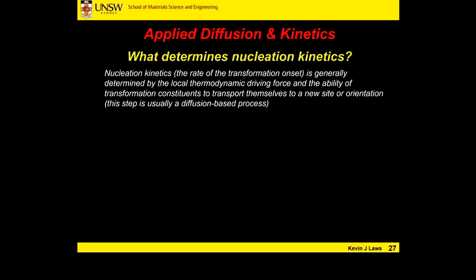But what I'm talking about here in terms of our free energy or our driving force, okay, is that for your reaction to proceed in a completely homogeneous way, it actually takes a lot of energy for the structure to locally overcome the barrier to nucleation. Okay. Once it is overcome, and it happens stochastically anywhere in the melt, which is probably what you were talking about a little bit before, the reaction will proceed quite easily. Okay. By having an impurity or a surface or an asperity on a surface, the localized activation energy for nucleation can be lowered. Sometimes it can be higher. Right? But if it is lowered, then that's going to be the site where nucleation is going to start and then proceed to growth.